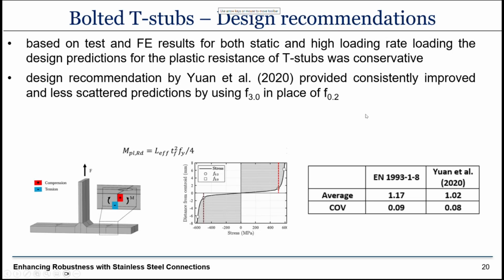Instead of using the 0.2% proof strength as a nominal yield strength for stainless steel, we propose to use the 3% proof strength, so the stress at which, upon unloading, we have 3% plastic deformation. And when we do that, we obtain much better results for both static and high strain rate results, provided we use the correct material properties for the high strain rate results. So provided we have a good predictive equation for the dynamic increase factor. So Eurocode is overly conservative, and with the proposal of using a higher proof strength, we get less conservatism and a slight drop in coefficient of variation.